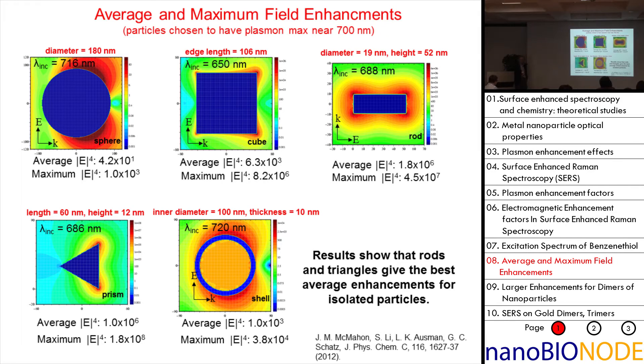Once we realized you can understand a lot of what's going on in SERS — not everything — in terms of this electromagnetic enhancement factor, that gave us confidence that we should just go off and calculate these average E⁴ and maximum E⁴ values for everything we could think of and see what comes out best. We did it for a bunch of silver particles that have plasmon maxima near 700 nanometers, and we found that the best were things like rods and triangular prisms. Anything with a high aspect ratio is about the same, and you can easily get average E⁴ of 10⁶ by solving Maxwell's equations and plugging in the experimental dielectric functions.